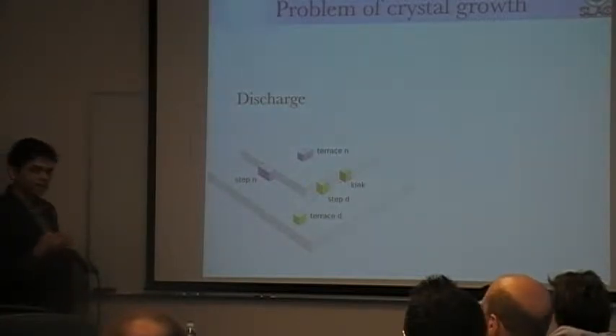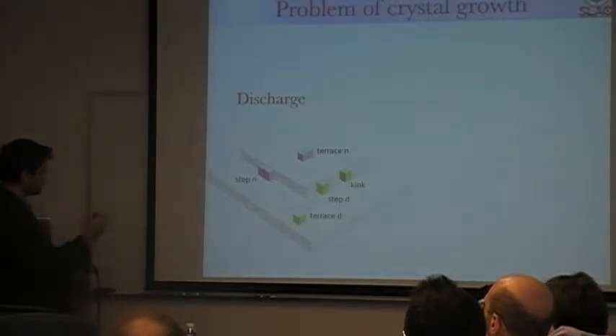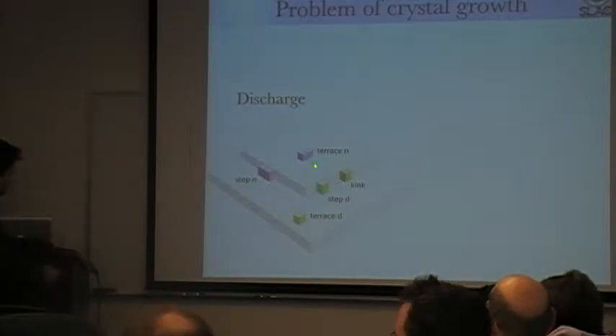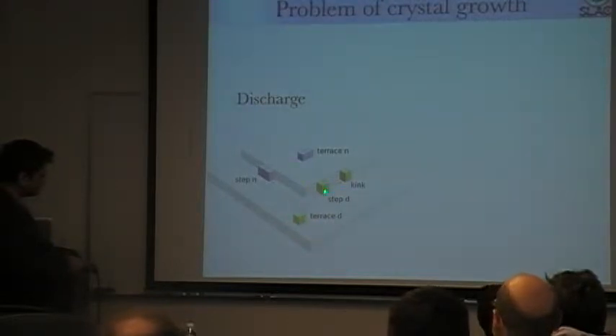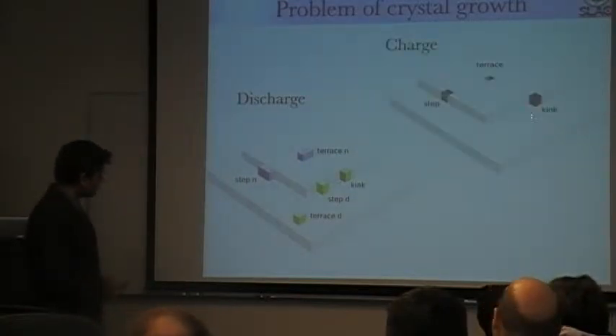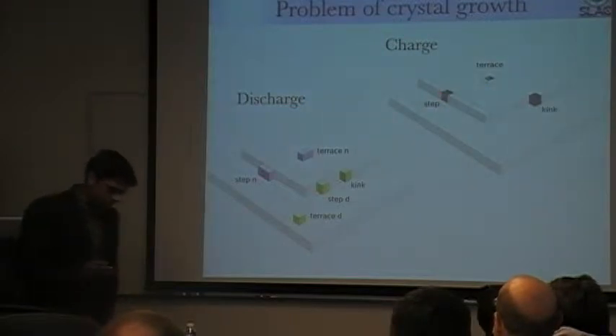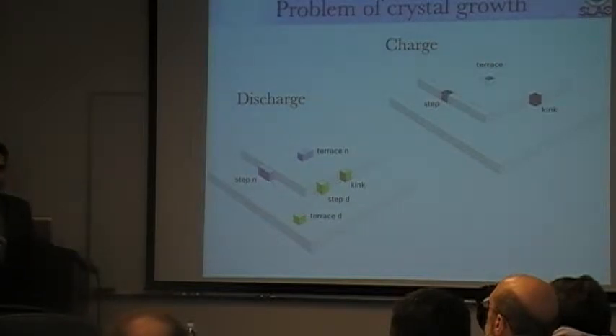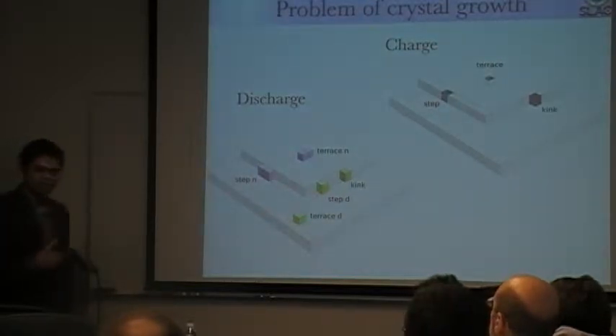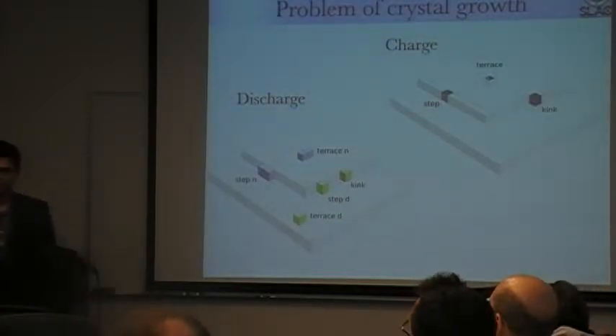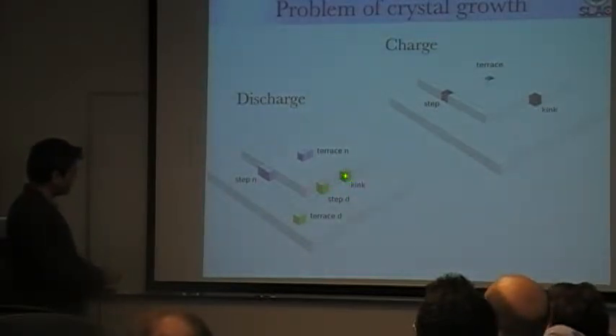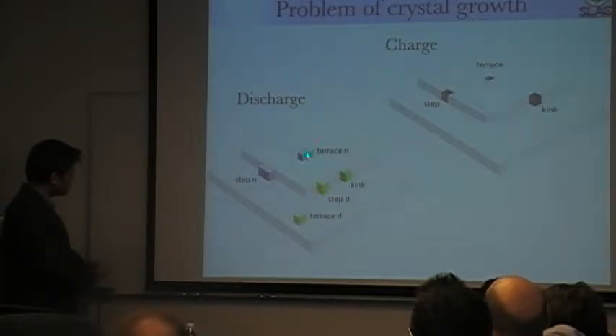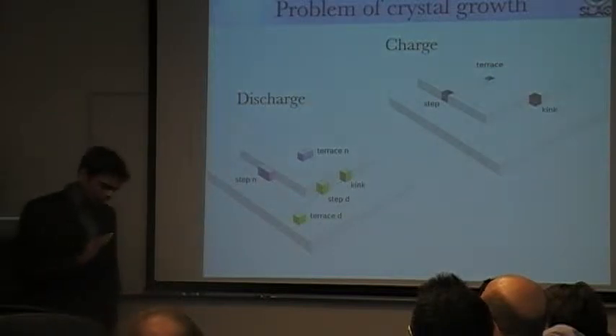We have a complicated high-dimensional crystal growth problem. Crystal growth can happen through many different pathways: nucleation on a terrace site, a step site, or a kink site; or diffusion from a terrace to a step site or from a step to a kink site before nucleating. Similarly, during charge, etching can occur on a terrace, step, or kink site. In electrochemical crystal growth, we're saved by the fact that reactions will run on the sites that have the lowest overpotential — the lowest thermodynamic and kinetic barrier. I'll show representative calculations on a kink site, step site, and terrace site; the trends are more or less similar across all explored configurations.